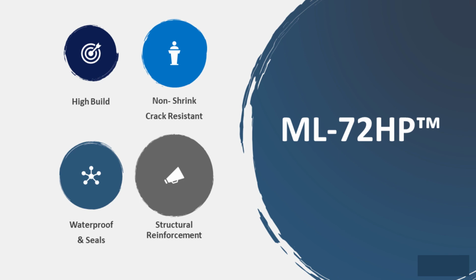The ML72 HP, the HP stands for horizontal pipe. It's very similar to our regular ML72. We've just put some added polymer into it, which not only makes it extra adhesive, but it slicks up your hoses on the inside to pump further distances, and it also helps so you don't get any cracking in it. It's a high build mortar.